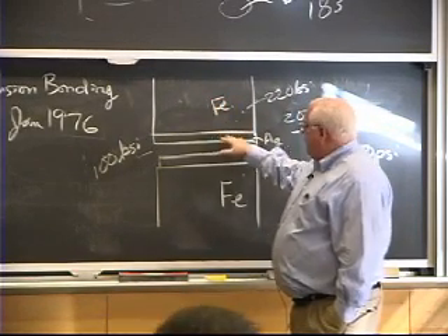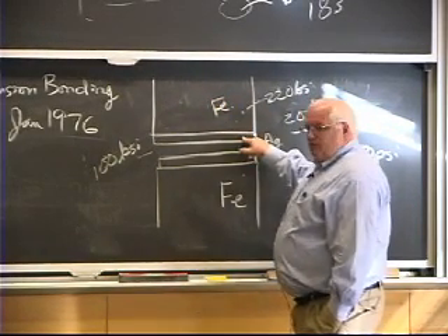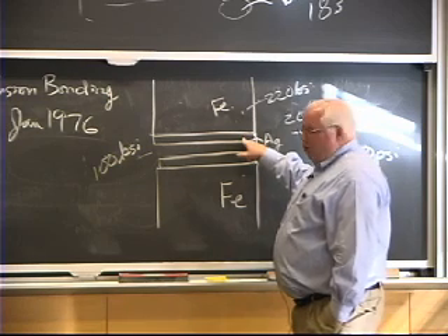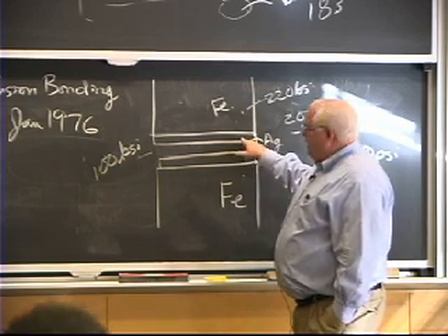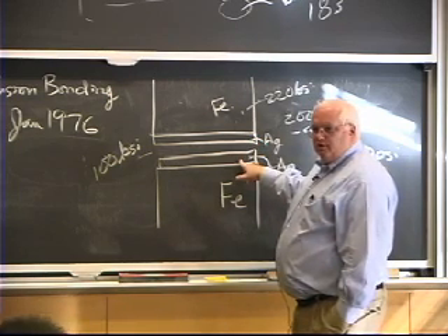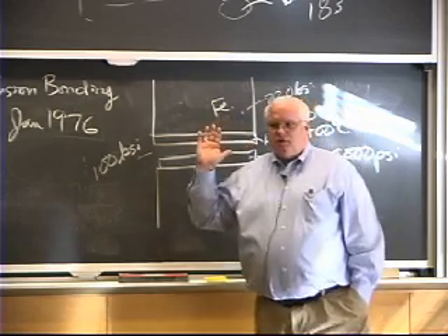You might be able to flux it away. Silver, on the other hand, forms an oxide, but the oxide in a vacuum will decompose at 400 degrees C. So you can evaporate away the surface contamination.